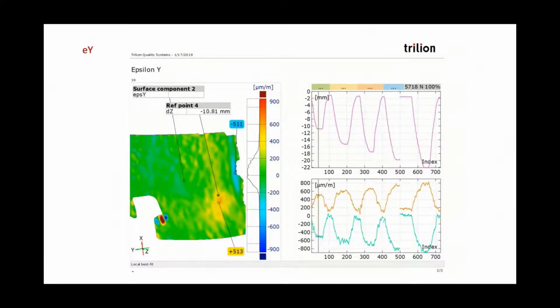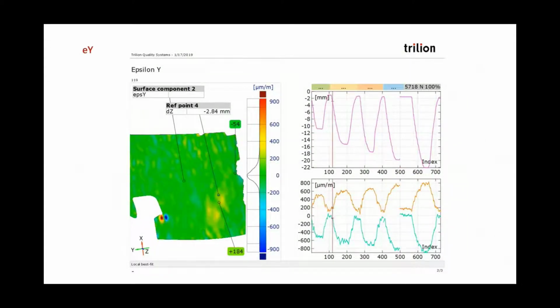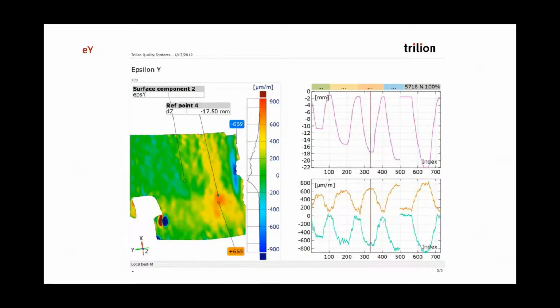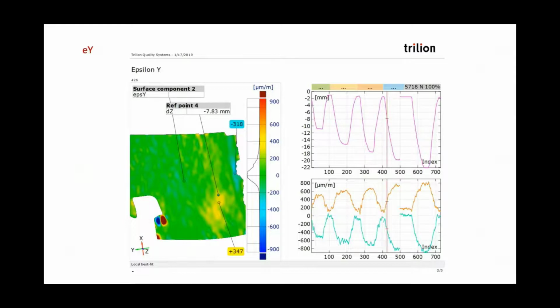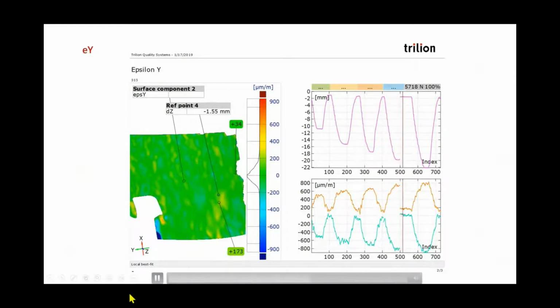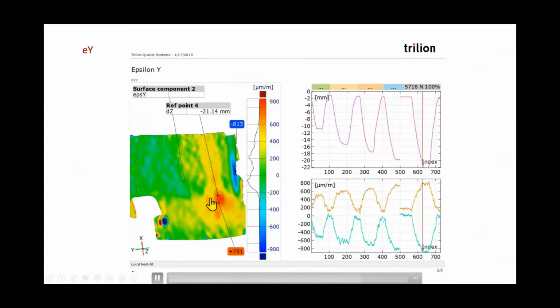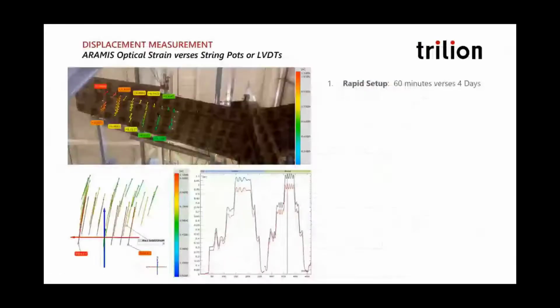And then when we get into the epsilon y, now it'd be a vector of strain that you're interested in here, and you're understanding exactly the strain fields associated with that vector of strain. And you can choose that orientation here. Here's the y vector in this case. So we're measuring the strain in this vector for the material.